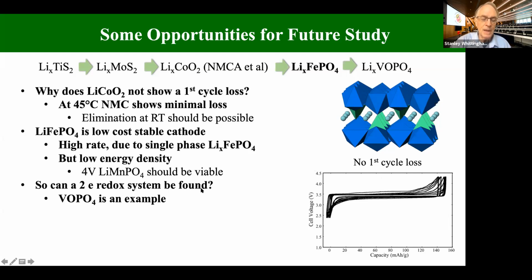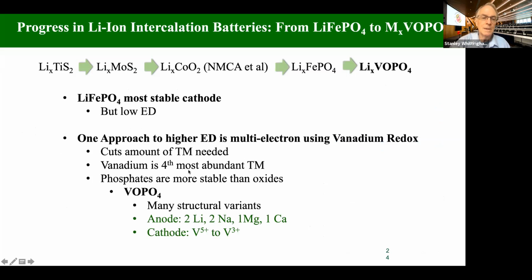But the real interest we've been looking at is, can we make a two-electron redox system? We chose vanadium because vanadium can easily go from +3 to +5 oxidation state. And we had some clues earlier on this might work. Despite a lot of people's concerns about is there enough vanadium in the world, there's more vanadium in the world than there's cobalt or nickel or copper. So it's the fourth most abundant transition metal. So I really discussed most of this already.